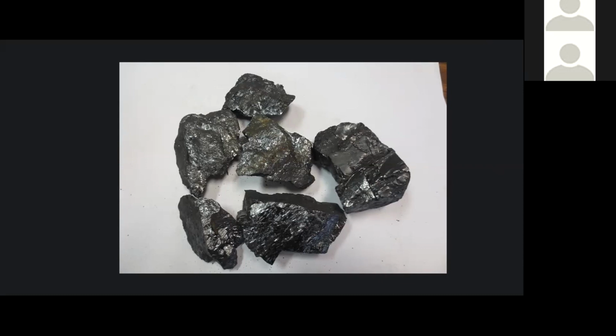Anthracite is a really peculiar fuel. It was nicknamed stone coal. Early attempts to burn it were so unsuccessful that they dumped it as ground covering for sidewalks because they couldn't get it to ignite. But for anthracite iron purposes, where you want to use the coal as a source of carbon for smelting iron, it was eventually discovered that if you heat the air up before it goes into the furnace, several hundred degrees, that was the temperature of the air necessary to get the anthracite coal to actually burn and do its job in the chemical reaction.